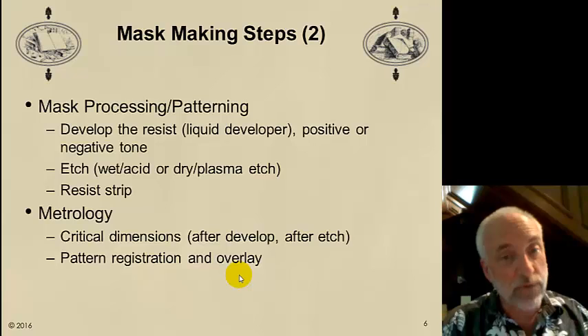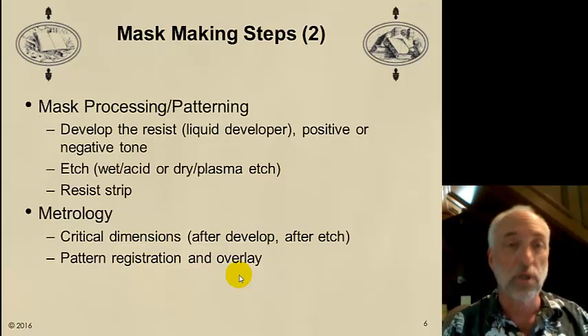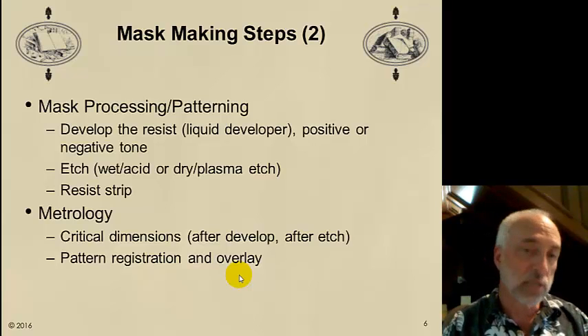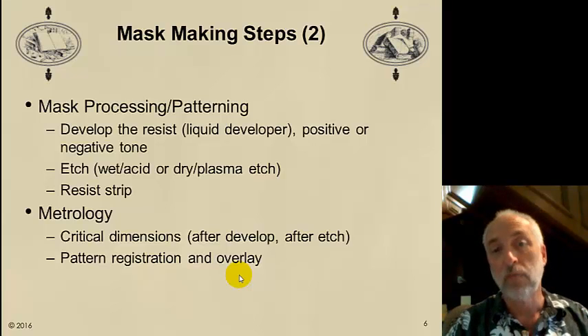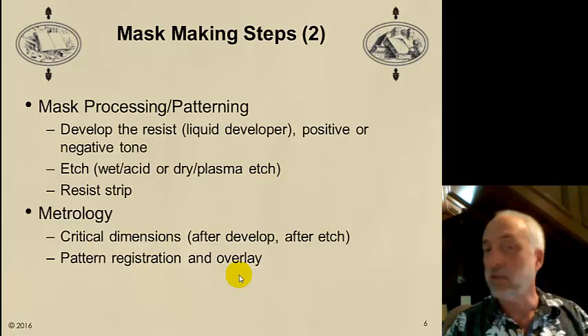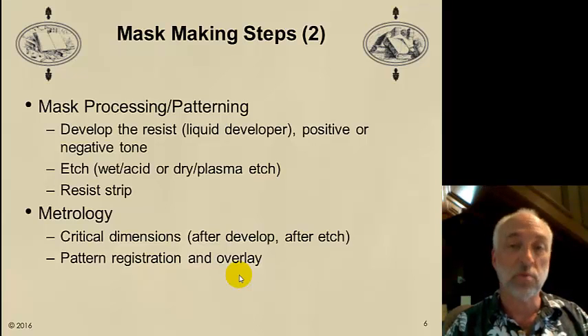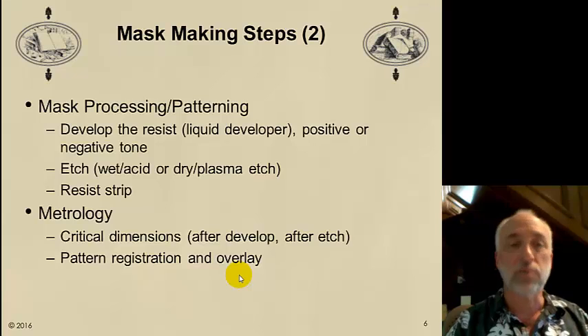We need to transfer those patterns into the absorber using an etch process. In the old days, we used wet etch, an acid that would etch, say, a chrome material. But today, with our small patterns, we almost always use a dry or plasma etching. Finally, we strip the resist away, and we've got our photomask. We then do some metrology.